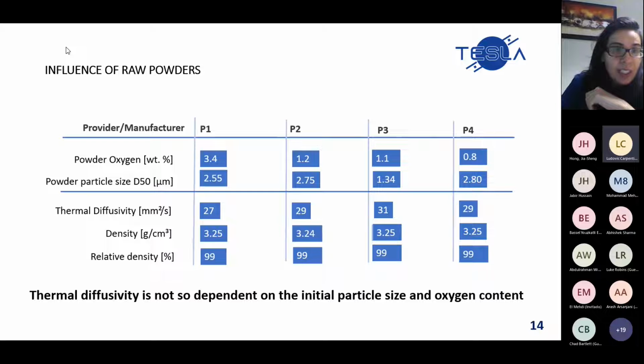We also studied the influence of the raw materials from different providers. With those providers, we have different amounts of oxygen content. Also, we did some measurements on the particle size. As you can see, the particle size tends to be around the same range. After sintering, we measured the thermal diffusivity of the material. We found that the initial particle size and the oxygen content, even if it fluctuates, doesn't impact the thermal diffusivity too much when we are thinking about the oxygen content in the surface layer that I showed in the past slide. However, for oxygen content in the lattice, the behavior will be quite different.